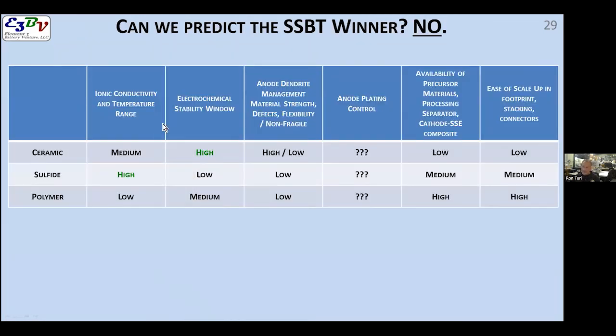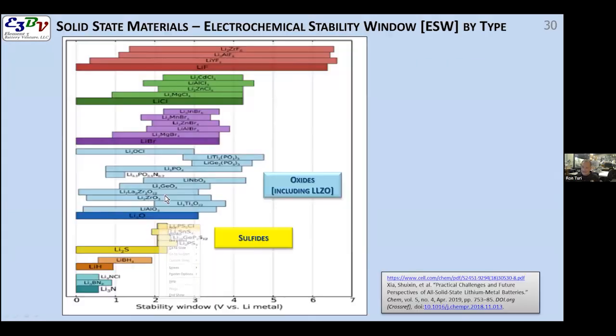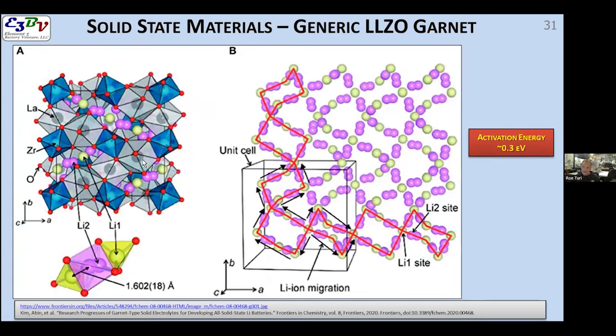If you take a look at the trade-offs here in the general buckets, you can get some idea of where this is all going. There's also the electrochemical stability window. That means on this side, you're worried about reduction with lithium, and on this side, you're worried about oxidation with whatever you're using for your cathode. And as you get up to higher voltage cathode materials, you can see the choices winnowing down. And some of these materials that you see here in the sulfide category don't do very well in terms of being stable for either reduction or oxidation. So these are some of the reasons that you have multiple compositions in solid state electrolytes. But again, this part of it is probably the best solved part. The dendrite growth and cycling part is the part that's probably least developed.